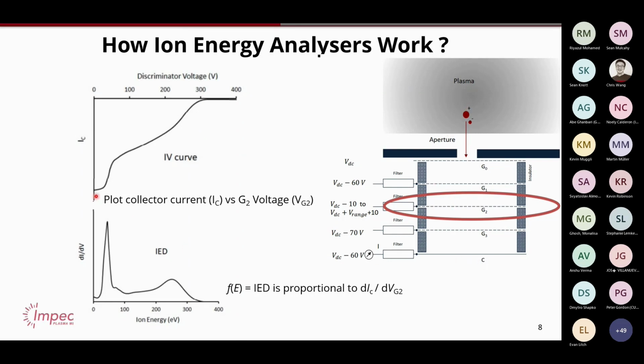I'm going to show you on this graph here. This is a measurement of the ion current coming into the sensor. Initially, lots and lots of current is coming in. Then you increase the voltage on this discrimination grid, and as you increase the voltage, you start to block the current. You keep increasing the discriminator voltage, and eventually you get no current at all. That means all the ions are being blocked at that point. Essentially, this is telling you how many ions you have at different energies.